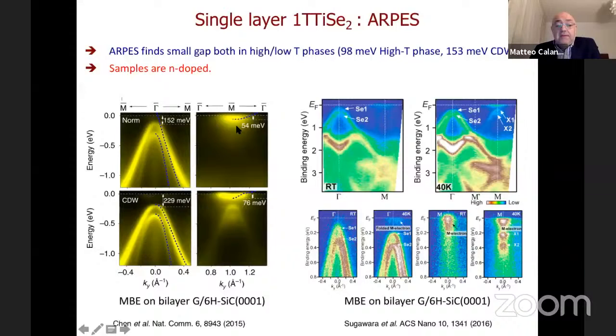If you lower the temperature, what happens is that you start to see shadow bands because the M point folds into the gamma point because of the 2x2 reconstruction, and you still see the doped band here. And there seems to be some kind of pseudogap, or gap, that opens between the partially occupied band and the selenium band totally occupied. And typically, the gap is 98 milli-electronvolt in the 1T phase and 153 milli-electronvolt in the charge density wave phase. So we are talking about a system that, if we had it in perfectly stoichiometric form, would be a semiconductor with an extremely small gap.